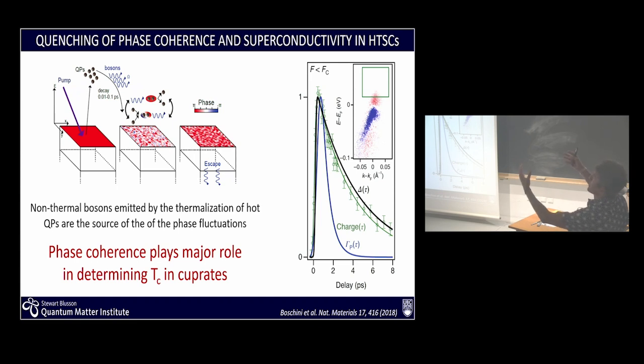Now, I want to stress that this is not thermal in a sense that, of course, we are creating hot quasi-particles. We see that the temperature of the system, electronic, goes up to above 60 Kelvin or so. That corresponds to a reduction of the gap itself. Now, on this plot, as a function of delay, we can plot in black the fit to the data from before for the gap itself, but reversed, and in blue, the lifetime effects, so the gamma p, the pair breaking scattering rate. So here the gap is decreasing by an effective 10%. Here I'm just plotting the data normalized from 0 to 1 and reversed so that you can compare them to the green data points. The green data points are the intensity measured here above the chemical potential.